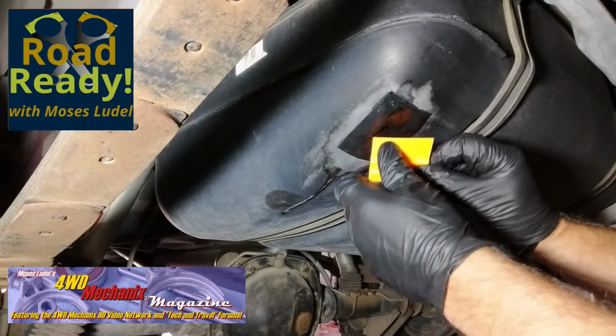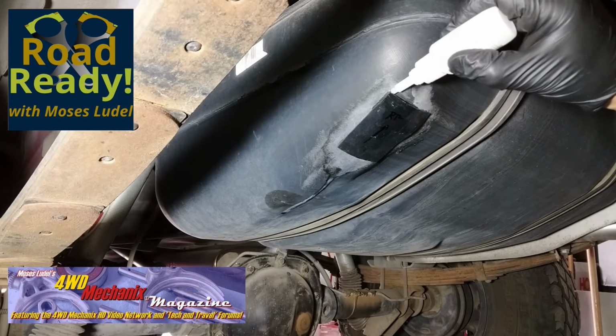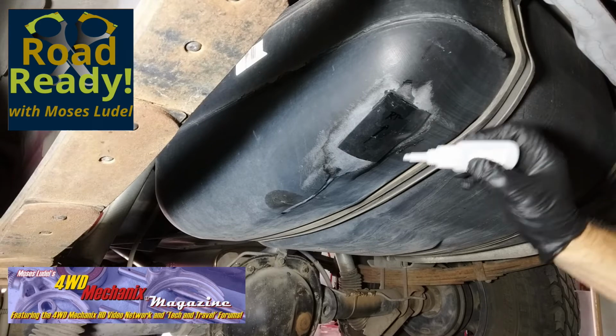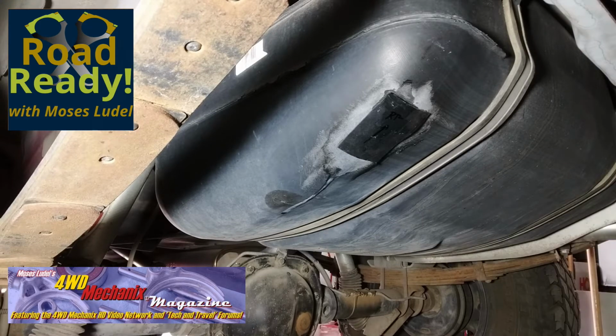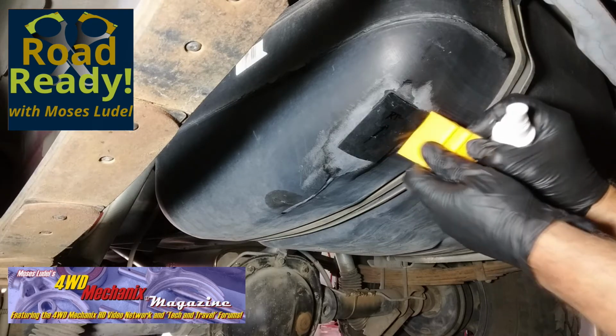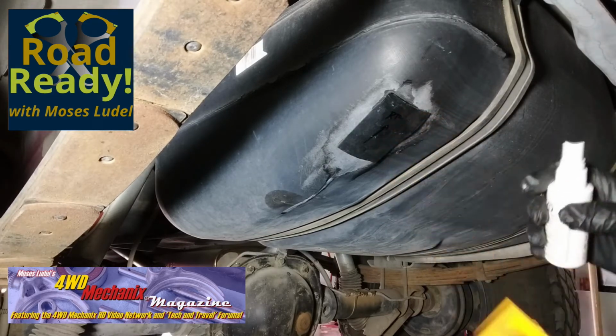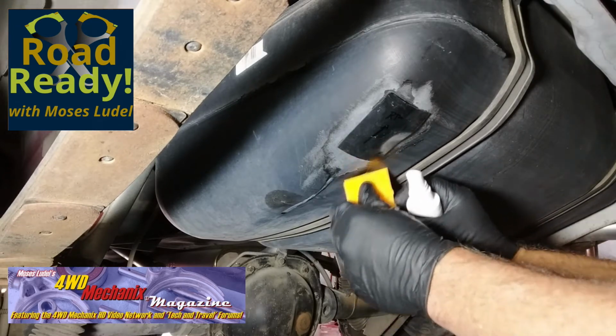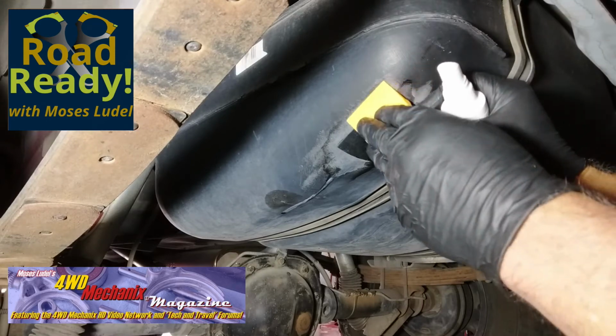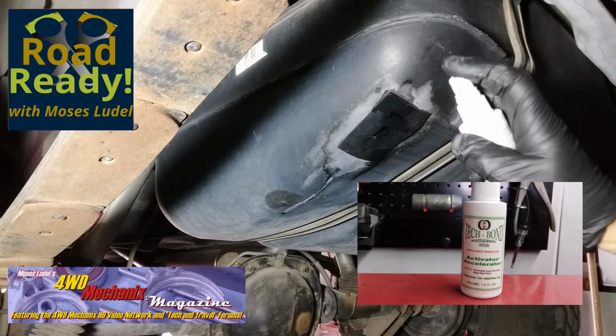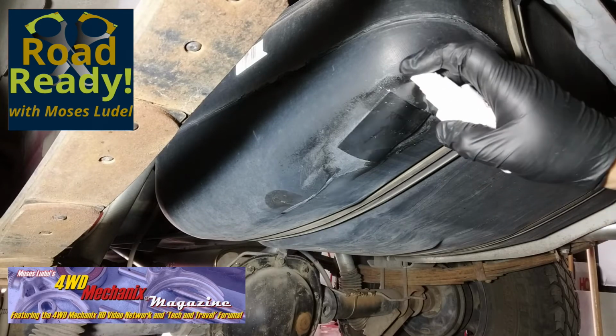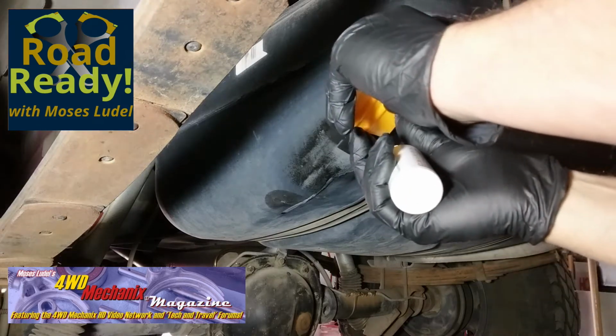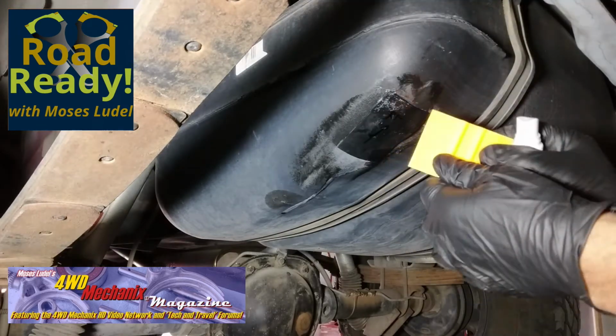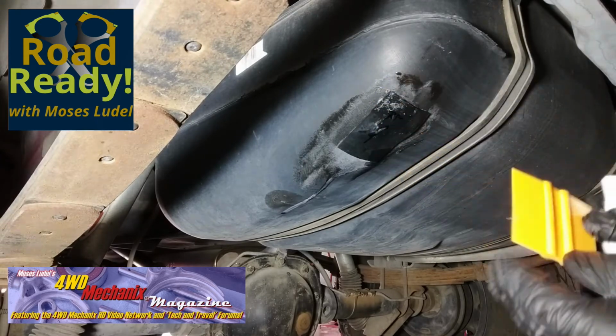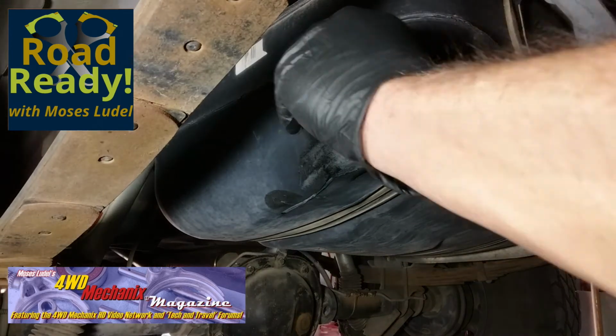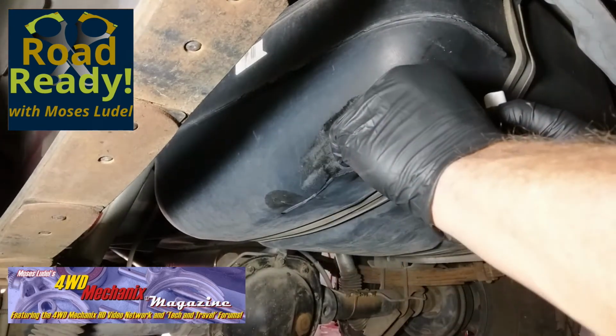Thoroughly bonded, the 2 mm thick FVMQ patch with additional thickness of Teflon is substantially thicker than the depth of the scrape. Tech-Bond uses fluorosilicone as their polymer of choice. During the manufacturing process, a surface of fluorosilicone is infused with side groups that strengthen the chemical and physical resistant properties of fluorosilicone. With these enhanced properties, the Tech patches have an excellent fuel, oil, water, and weather resistance, resistant to most chemicals. Polyfluoroalkyl side groups protect the fluorosilicone from damage from water, weather, gas, oil, all hydrocarbons, salt, and humidity.